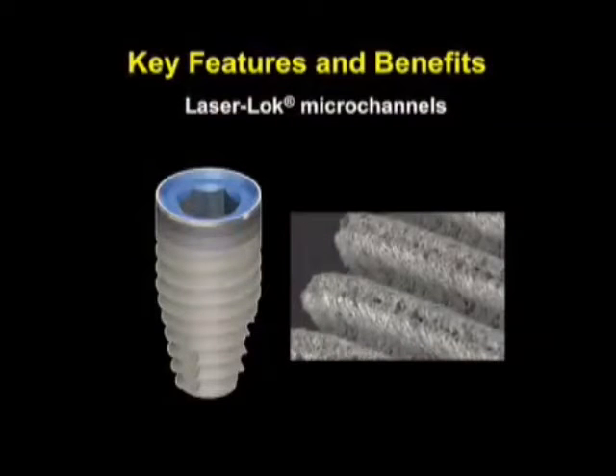When we look at the product, the collar is divided and has two laser cuts at different dimensions: one being 12 microns to encourage osteoblasts or bone connection, and above it there's a lesser cut of 8 microns. The theory is that bone would attach at this level and we'd have a true connective tissue attachment at this level, and there would still be room for a junctional epithelium.